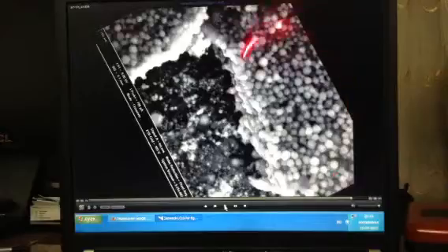For example, on this photo we can see that the external topology is a smooth layer of nanoparticles, a very homogeneous layer. But inside of the track we see random and chaotic topology with many defects, unhomogeneous, with the patterns of melted copper, like here. So different mechanisms generate different topologies.